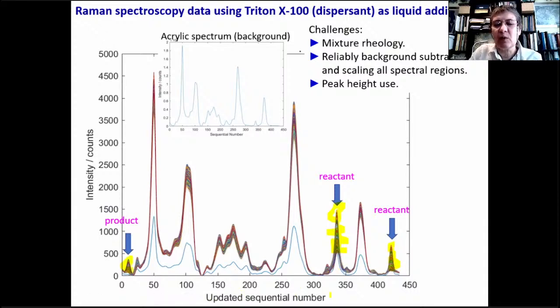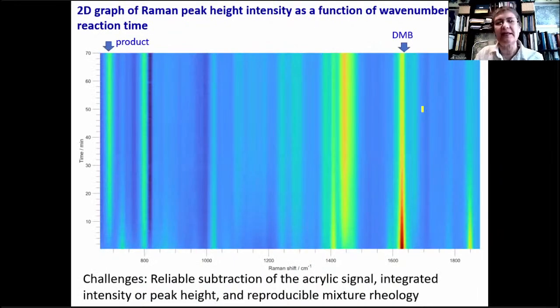So this is a sequential number that we use for the analysis of the data, but it has an equivalent wave number there. And in theory, quantitative Raman spectroscopy is not done with the peak heights, it's done with the integrated intensities of the peaks. Which would mean that we have to integrate the signal between certain wave numbers, and we have not done that yet. So this is a 2D graph of the Raman peak height intensity versus the Raman shift.